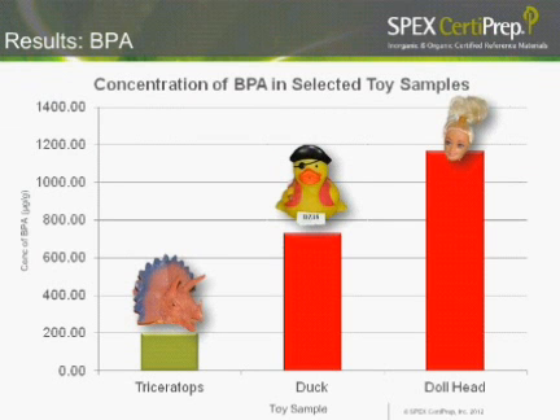Since we were running in scan, we were able to see the Bisphenol A, and we found that we had three PVC toys that contained measurable amounts of Bisphenol A, with our Triceratops figure at about 200 micrograms per gram, our friend the rubber duck at almost 800 micrograms per gram, and the doll's head at almost 1,200 micrograms per gram of Bisphenol A.